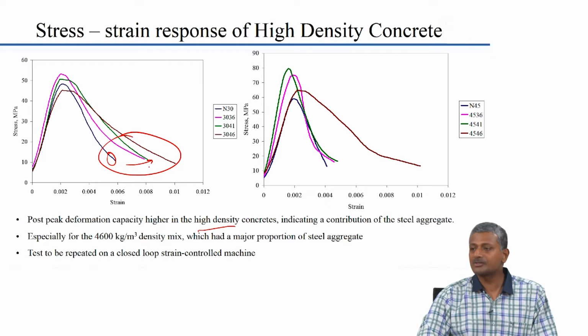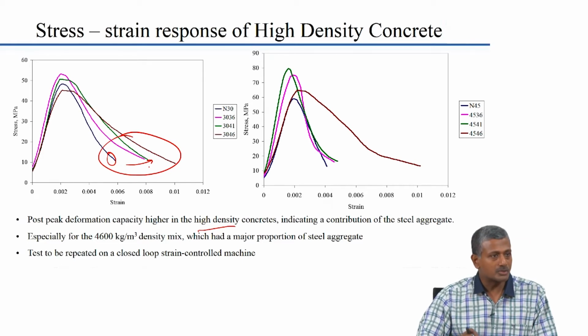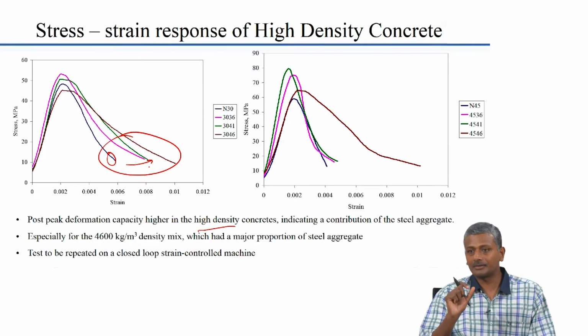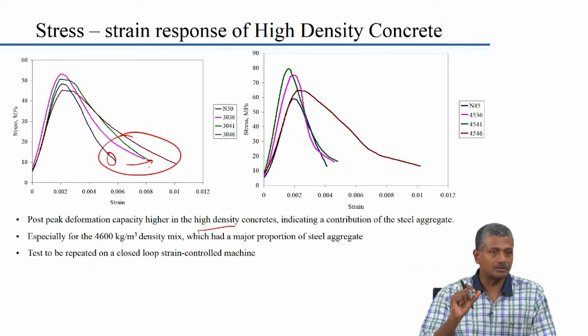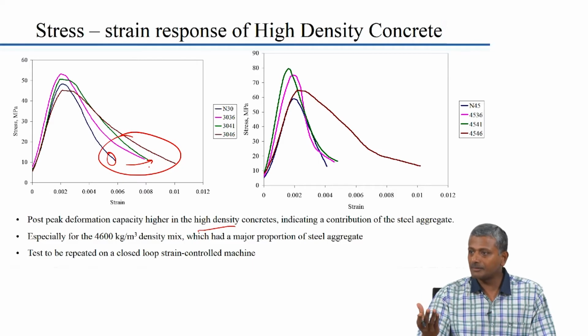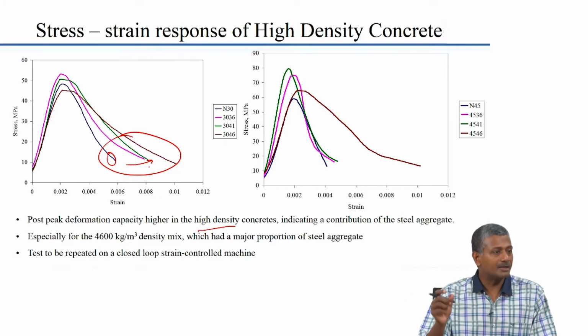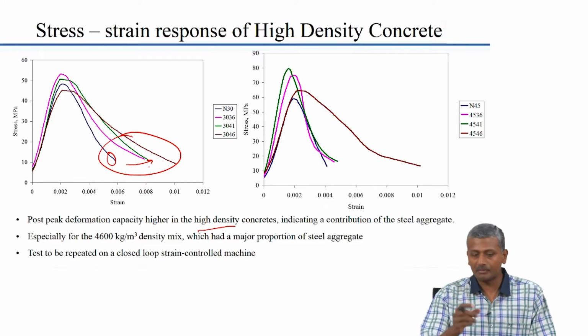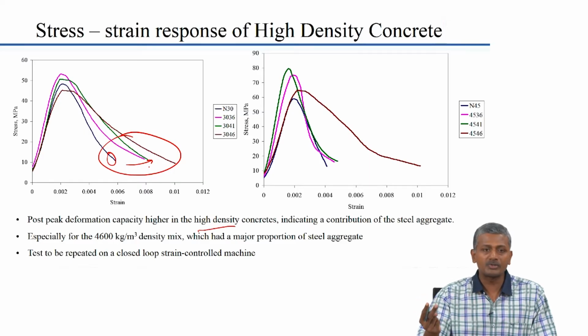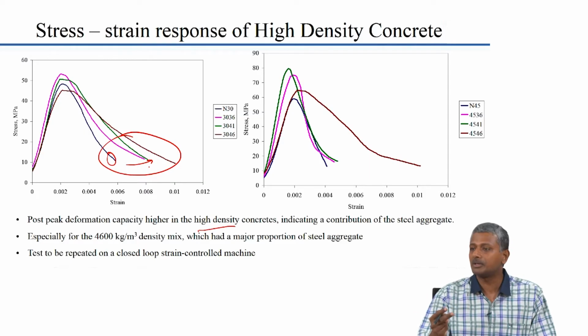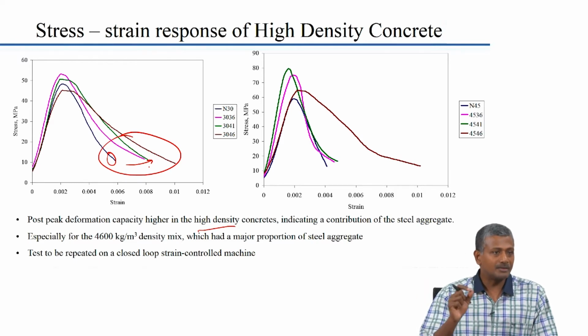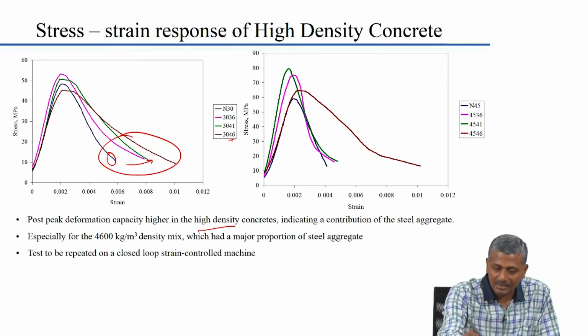Now, that in some ways could be attributed to the fact that we actually used steel inside these as aggregate. Inside the high density concrete we actually use steel as aggregate. Now, instead of using steel based raw materials like hematite or magnetite as aggregate, you can also use cut rods of steel and include them in aggregate sizes. For example, here we had used two different rods, one was an 8 millimeter diameter rod and one was a 20 millimeter diameter rod. Each were cut to a length of about 20 millimeters to almost get aggregate sized particles from the steel, and these were included to ensure that we were able to get densities of the order of 4.6 grams per cubic centimeter also.